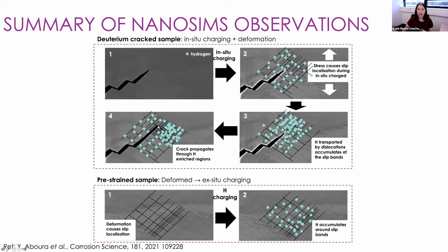And then what happens is our crack is going to propagate through those really hydrogen-enriched regions and propagate the crack further. Compare that to our pre-strain sample, where we deformed it and then charged it without any additional straining. We do still see hydrogen accumulating at slip bands, but not to the same extent.